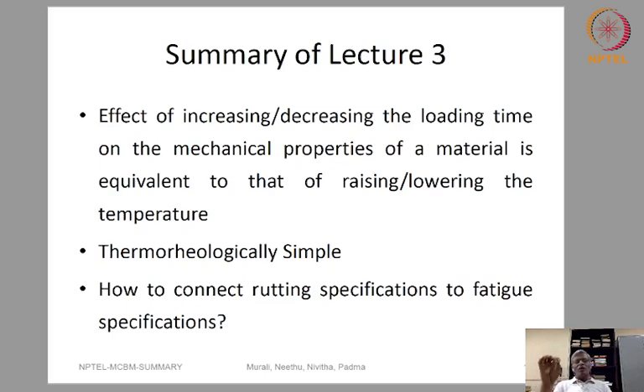In fact, the summary of lecture 3 can be given in one single sentence. The effect of increasing or decreasing the loading time on the mechanical properties of a material is equivalent to that of lowering or raising the temperature. So, if you understand this first sentence, you have more or less understood the time temperature superposition principle. Now, the most important thing is, this principle is valid only if the response of the material is thermorheologically simple.